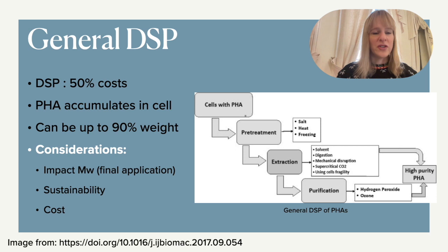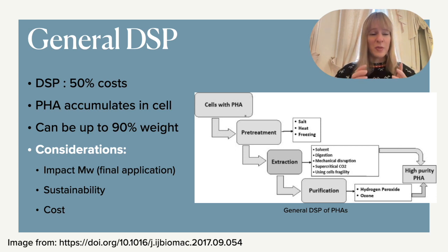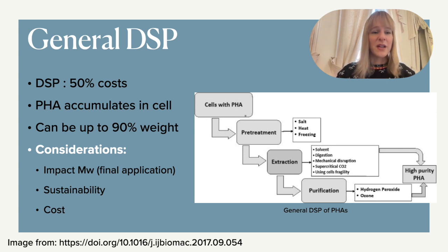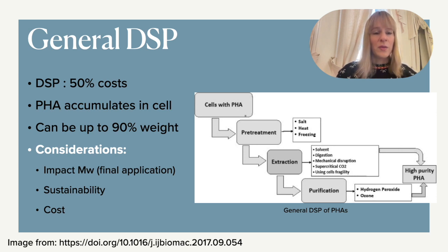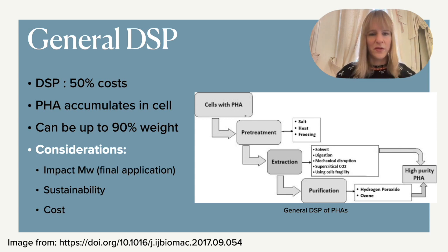Looking at the general DSP, as mentioned, costs can be substantial. Reviews indicate it can amount to up to 50% of the total cost in the case of PHA. PHA is stored within cells and can accumulate up to 90% of the cell weight, so you can imagine the very large quantity you need to deal with.